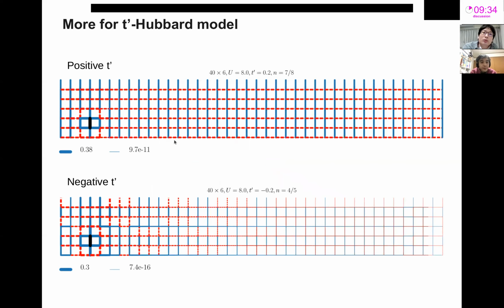For example, on the width 6 cylinder with positive T-prime, you can get this kind of perfect D-wave superconducting state. But with negative T-prime, you have this complicated pairing correlation - it's locally like D-wave, but it becomes very noisy at long range.